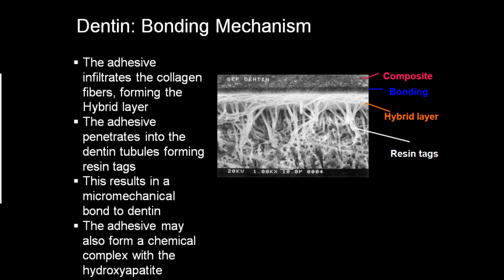So that's why if we can establish this very sound and very predictable hybrid layer that you see there between the dentin and the composite, so that we do not have that infiltration, we will eliminate the micro leakage and negate completely the problems of post-operative sensitivity. So that's why it's important these self-etch adhesives allow us to do that in more of a predictable manner than what we get with our total etch on the dentin.